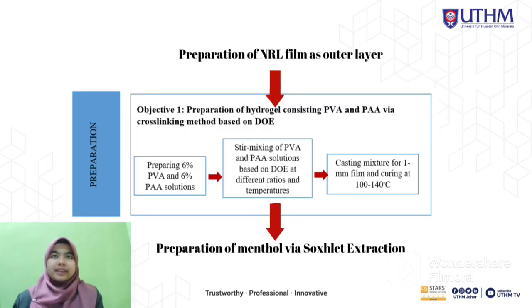Next for the method is the preparation of NRL film as the outer layer, and then after making the outer layer, the preparation of hydrogel consisting of PVA and PAA via the crosslinking method based on DOE. First of all, I will prepare 6% PVA and PAA solutions separately, mixed with distilled water. Then I will mix the PVA and PAA solutions based on DOE at different ratios and temperatures. After that, I will cast the mixture at 1 mm thickness and cure it at 100 to 140 degrees Celsius.